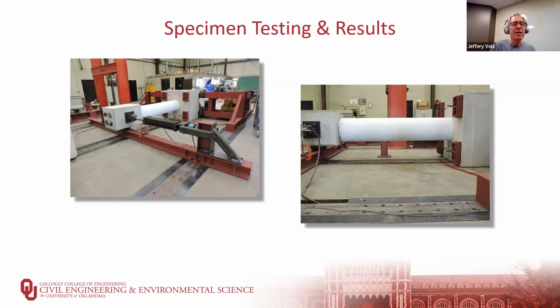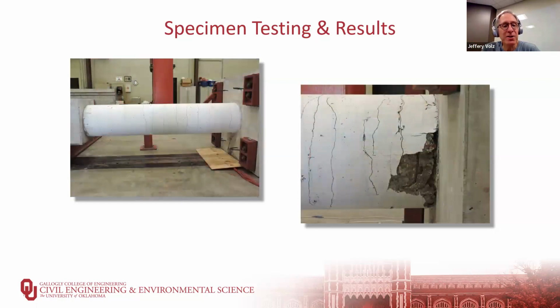So here we have the reinforced concrete column. Typically, when we test reinforced concrete columns in this manner, we will paint them white with a combination of white paint and water, to make the cracks more evident during the testing. So here you've got the column ready for testing. We started to cycle it. On the left are some of the initial cycles.